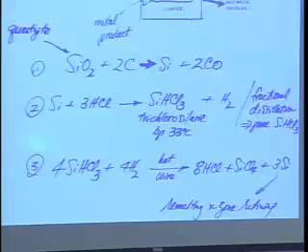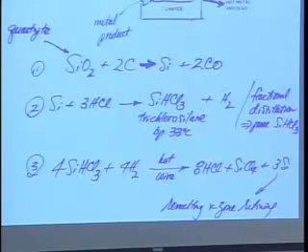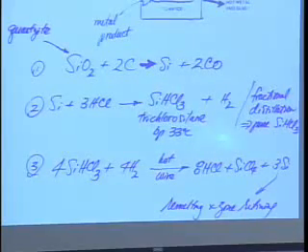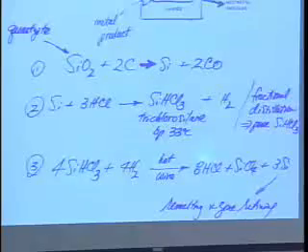So what can you do? Well, what happens to the iron? What happens to the aluminum? What happens to all the other crud? It doesn't form this. So now you can selectively transfer with minimal energy the trichlorosilane, fractionally distill it to get very, very high purity trichlorosilane. Then you go back and you convert to silicon.